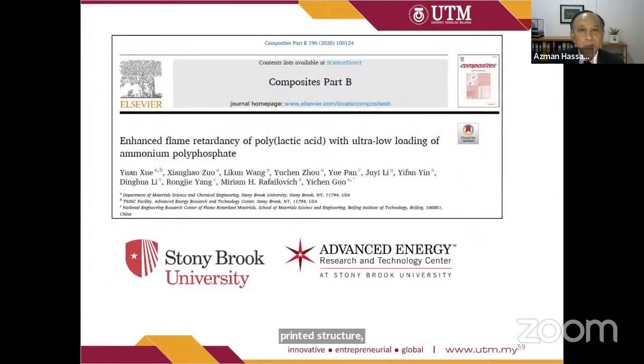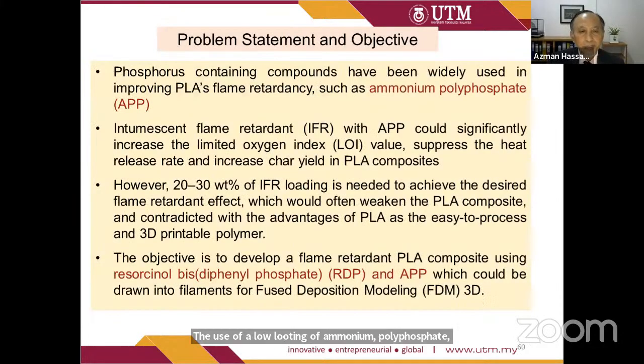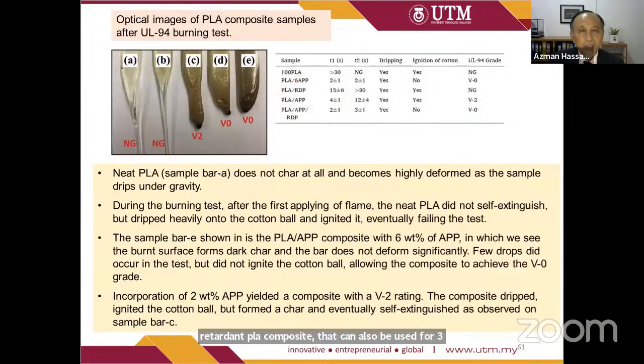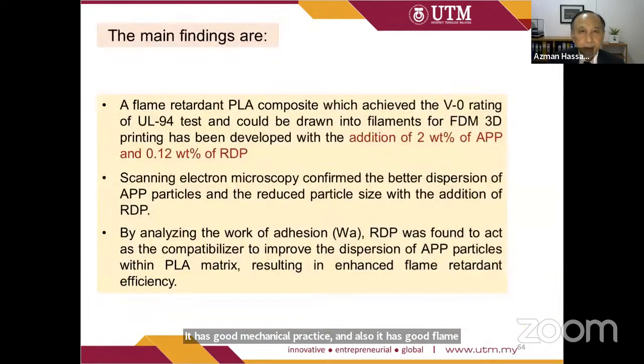And the last one is the use of low loading of ammonium polyphosphate. It has been shown that by the simultaneous use of resorcinol bis-diphenyl phosphate, RDP, and APP, they have produced a good flame retardant PLA composite that can also be used for 3D printing. It has good mechanical properties and also good flame retardancy. Okay, so these are the main findings. The formulation is the use of 2% of APP and 0.12% of RDP.